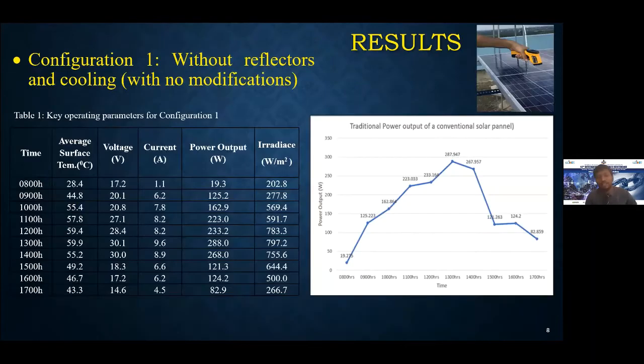So these are the measured results that we came across when using configuration number 1. Now, these results are without any modification to the panel. So these results give a clear understanding about the normal power output of the solar panel. If you have a close look on the time, the maximum surface temperature rises to about 60 degrees Celsius. And then the maximum power output of the normal conventional solar panel is 288. So you can see the graph also.